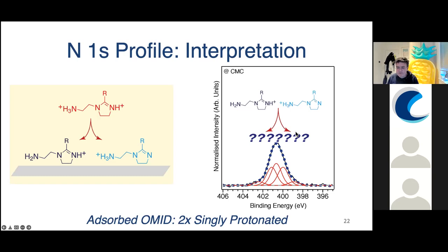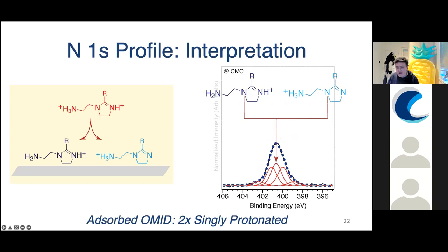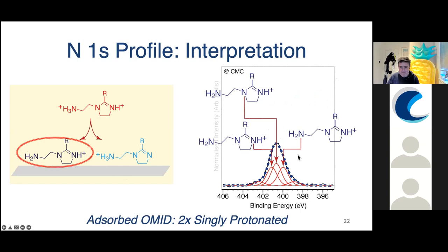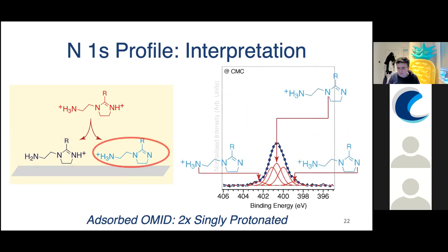Let me try and take you through our interpretation of the nitrogen 1s signal that justifies that. This central peak is due to this tertiary amine nitrogen, which is common to both. That's never protonated, so both molecules on the surface have that. If we look now at the dark blue molecule with the imine protonated, we have two other signals, the protonated imine and the primary amine, that's here and here, and they're equal intensity and slightly less intense than the central peak. And as regards this one, these outer two peaks are the protonated primary amine and the unprotonated imine. So we've taken account of all those peaks and the intensities are consistent with this interpretation.